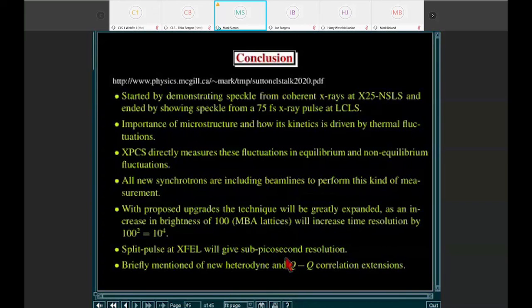CDI takes full advantage of the speckle pattern to reconstruct and make a microscope. XPCS just uses very simple information about how the intensity changes in a given speckle. But there's a lot of information in between these two limits, and we're basically pursuing various techniques for heterodyning to get more interesting time constants and actually access to the phase, as well as looking at higher order correlation functions, which will give us more information of what's going on. And so I think that's a good point to stop.